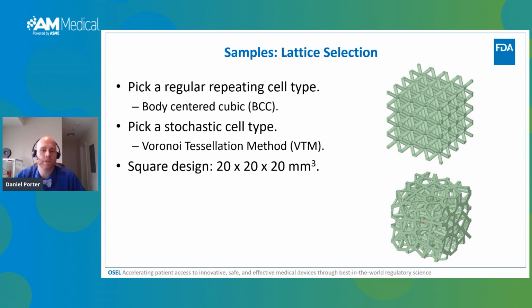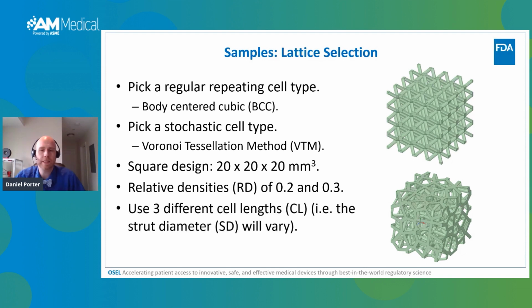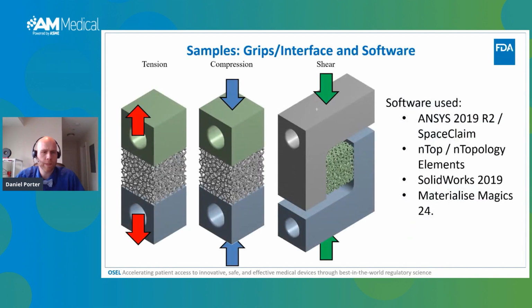Each of our lattice samples is 20 by 20 by 20 millimeters. We have two different relative densities, 0.2 and 0.3. And within each one of those relative densities, we adjust 3 different strut diameters while maintaining that relative density. So the cell length and the strut diameters vary just to maintain those relative densities. What type of loading modalities are we doing? We're doing, as I said, tension, compression, and shear. So this gives you an idea of what our full samples look like and the grips attached to the lattice samples.